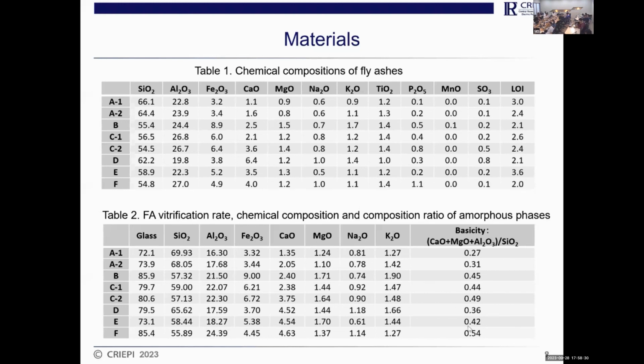And table 2 shows the amount of glass in the fly ash, noted as the vitrification rate. The amount of glass is from 72 to 85%. And I also show you the basicity. Basicity is the ratio of calcium, magnesium and aluminum to silica. The basicity is from 0.27 to about 0.5. There is much difference among these samples.